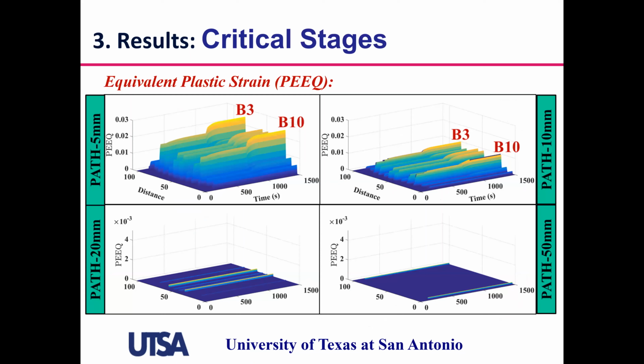Another measure that we used to capture these potential locations of cracks was the equivalent plastic strain. And I particularly like this measure because the stresses are time dependent, so they vary up and down during the simulation, but the equivalent plastic strain keeps accumulating. So it's a measure of the deformation gone through by the material throughout the simulation.